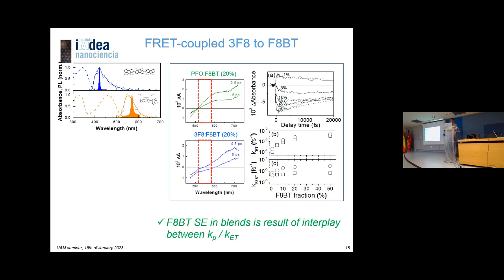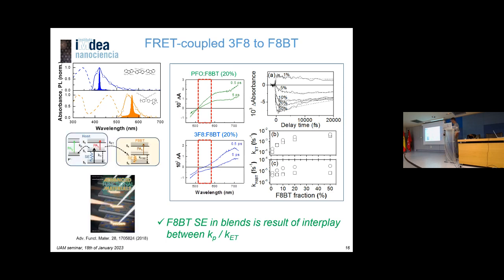You can now reduce the concentration. If you reduce the concentration, the transfer rate is going to be slower, meaning this build-up takes longer. At some point, if you go from 5% to 1%, you no longer see a change of sign, no longer have stimulated emission.